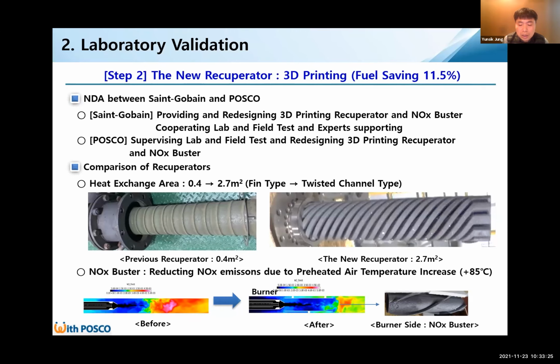The newly designed recuperator has much more heat exchange surface area compared with the previous version recuperator. The fin-type heat exchanger has 0.4 square meters of heat exchange area. The new one has 2.7 square meters of heat exchange area. In addition, a NOx Buster is installed and tested to reduce NOx emissions due to the preheated temperature increase.